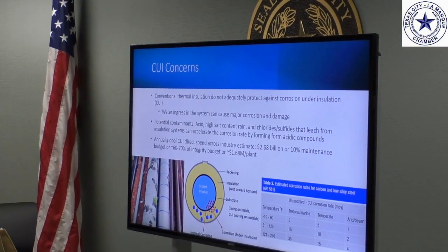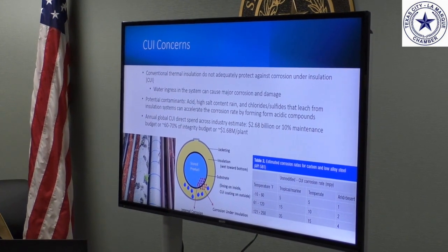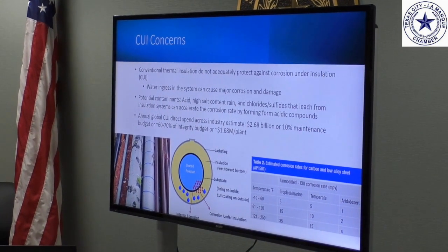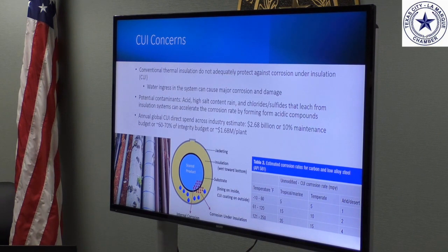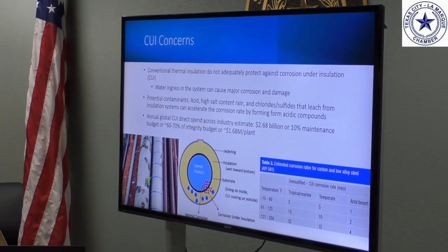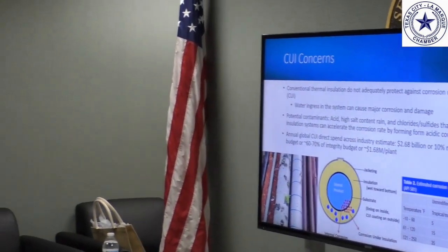You're all probably aware of some of the challenges that are present with CUI. Water is our enemy. Water and oxygen are the two main players that cause CUI. And it's worse when it comes to insulation, insulated vessels and so on. And temperature plays a big role as well. In addition, when you have covered insulation, you could have high concentrations of acids, salts, chlorides, and sulfates, which are big enemies there. If it becomes acidified, it's even worse.